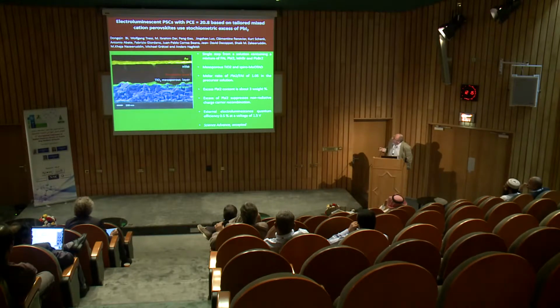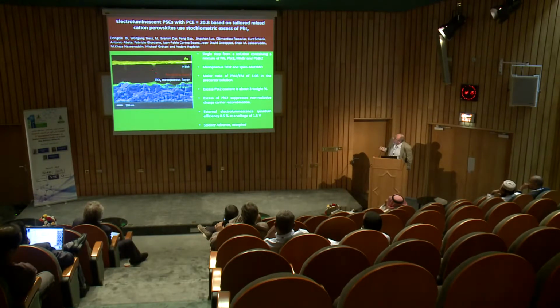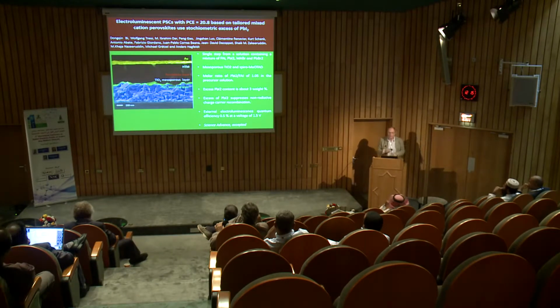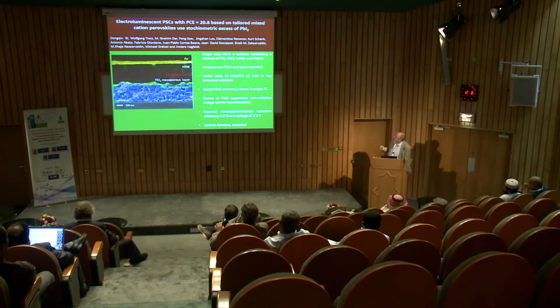So we have, here is the FTO, we have a blocking layer of TiO2 by spray pyrolysis. We have a quite thin layer of the nanoparticles of TiO2, about 200 nanometers. That includes perovskite in the pores, but most of the perovskite is in the compact, what we call the capping layer on top, about 400 nanometers. The hole conductor, and then the gold as a contact. So this is optimized with the recipe of the composition of the mixed perovskite, and we do see also that we need a little bit of excess of lead iodide. That helps, and we think we have an excess of lead iodide of about 3% to 8% in the total perovskite structure. We can tell that the lead iodide excess is beneficial.